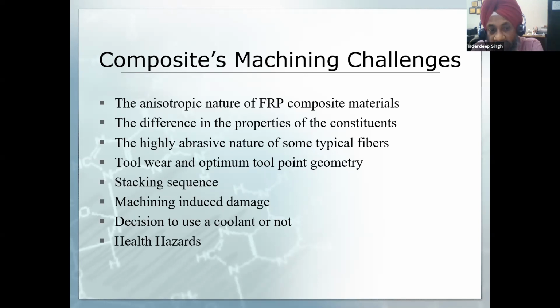So if you have a very abrasive fiber, tool wear and optimum tool point geometry become a very important point, because if your fiber is very sharp and abrasive, it will lead to a lot of tool wear, and in order to avoid the tool wear, we would like to design our tool in a way that the wear can be minimized.